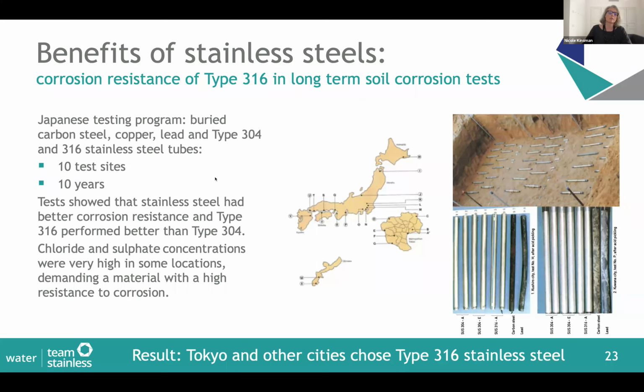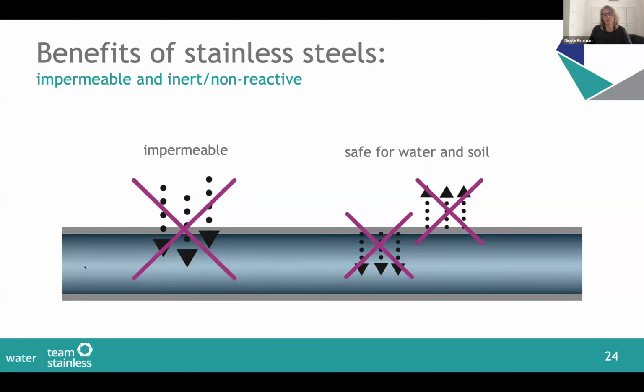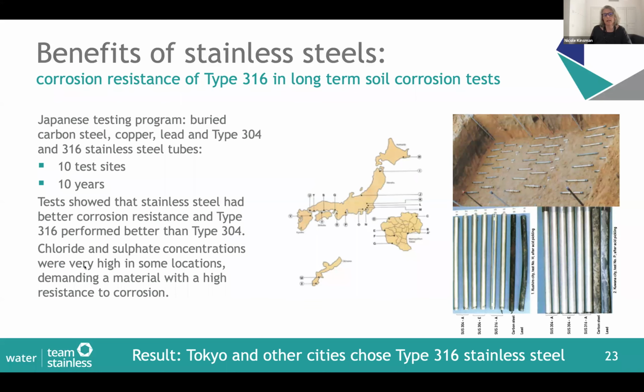The test showed that stainless steel had better corrosion resistance than some of the other materials that were tested. And type 316 here performed particularly well, better than type 304. Because some of the chloride and sulfate concentrations in the soils were quite high in some locations, a material with particularly high corrosion resistance had to be selected. And as a result, Tokyo and also other cities chose type 316 stainless steel for the service pipe application.